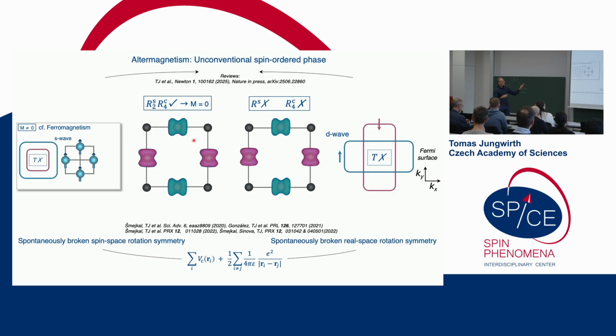But it's of a very different form in ferromagnets, because in ferromagnets, in the momentum space, what we have are the majority spin and minority spin Fermi surfaces, while the shape of the Fermi surfaces, or the orbital part, is actually still symmetric with respect to the crystal. We don't break the real space rotation symmetry, but we deform the Fermi surfaces in terms of their volume. So one Fermi surface becomes small and the other one becomes large. So we break the time reversal symmetry by simultaneously creating the net magnetization. While in altermagnets, we break the time reversal symmetry, but we have another symmetry that protects zero net magnetization.